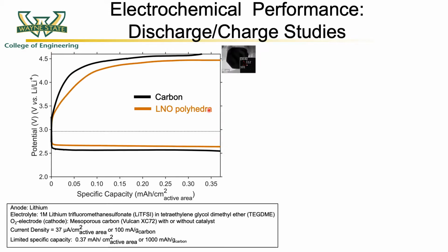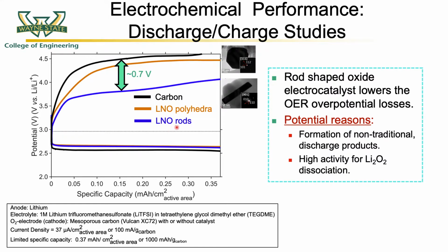Upon incorporation of polyhedral shaped La2NiO4, a small reduction in the charge overpotential is observed. However, upon incorporation of rod shaped La2NiO4, a significant reduction in the charge overpotential is observed of roughly 0.7 volts. Potential reasons for this reduction include formation of non-traditional discharge products such as LiO2 during discharge, which consequently